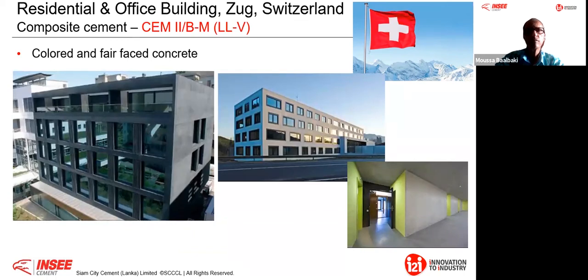This is in Zug. Again, it's a fly ash and limestone composite cement. And when you look at the color here, this is not the normal color of the concrete. A pigment has been used because I know in Sri Lanka very often people like darker. But the color has nothing to do with the quality of the cement. I can have off-white, beautiful cement with high strength, high durability. We can just put a little bit of iron oxide and turn the cement darker, but that doesn't mean the quality has changed. The color is just the iron content, but this has nothing to do with the strength. Here, architects use color to express a certain warm or cool feeling of the object.